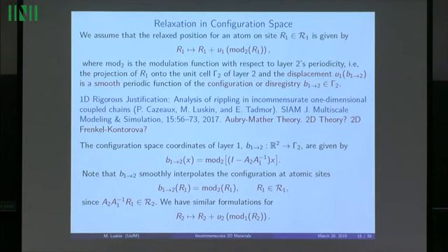Because if we just moved through space without interpolation, you'd have a disregistry that was oscillating on the atomistic scale. But now when you do smooth interpolation, we get rid of that oscillation. Anyway, so this is our continuum disregistry.